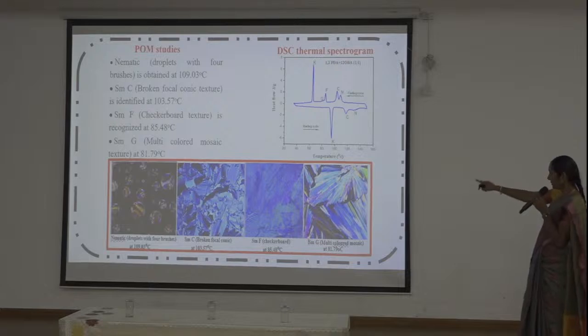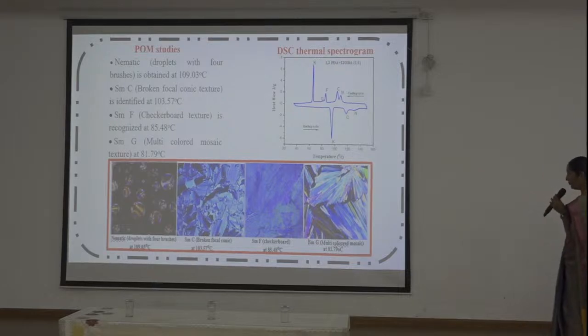Gradually decreasing the temperature, I found Smectic F. This type of structure is called the checkerboard structure, observed at 85.48 degrees centigrade.